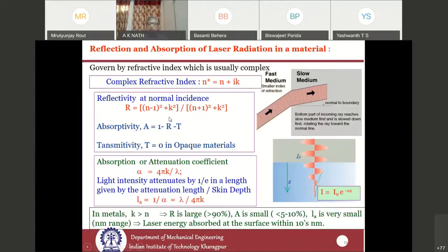So absorptivity depends on the complex refractive index of the material, and this also determines the absorption or attenuation coefficient. This alpha is a characteristic of the laser and material, given by 4 pi k by lambda, where k is the imaginary part of the complex refractive index. The inverse of this tells how quickly laser energy gets absorbed within the material, known as the attenuation length, sometimes also called the optical skin depth.